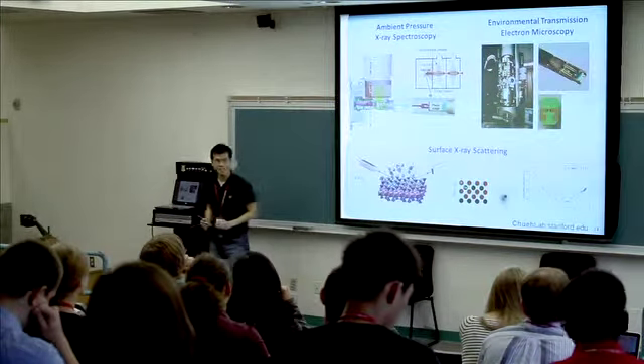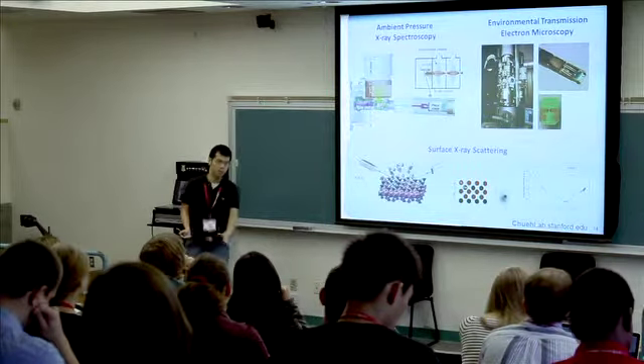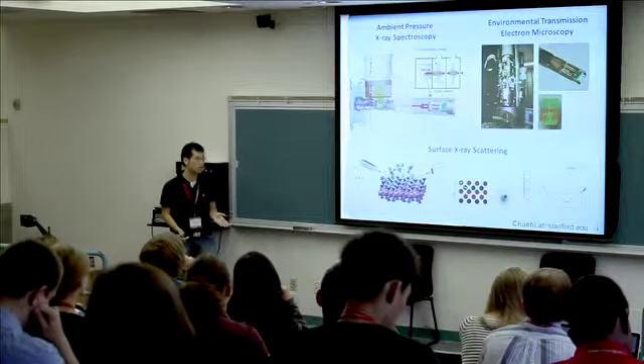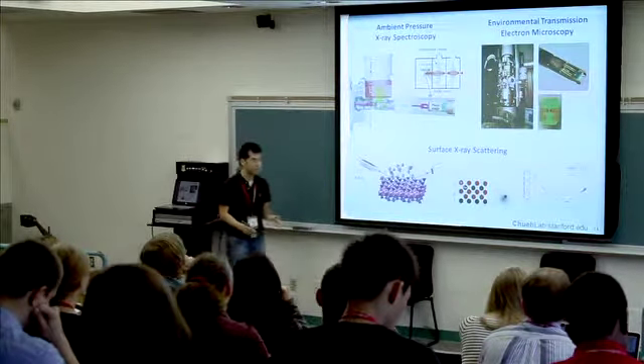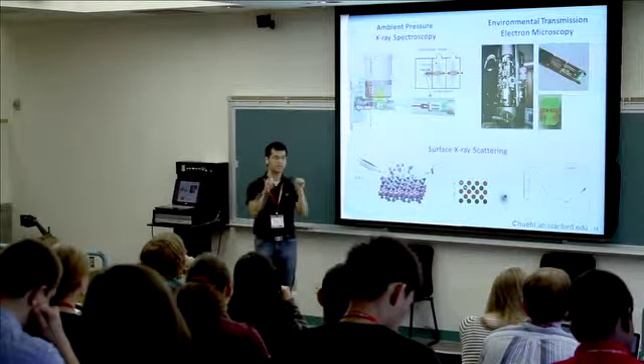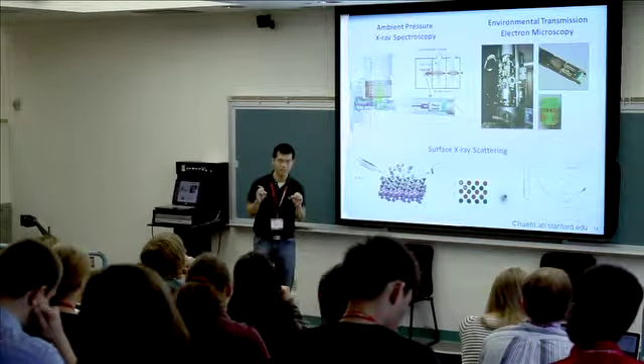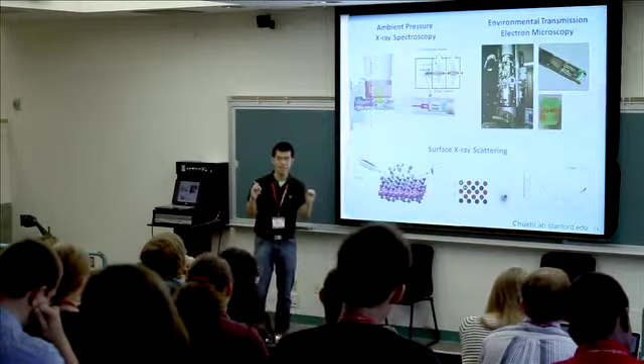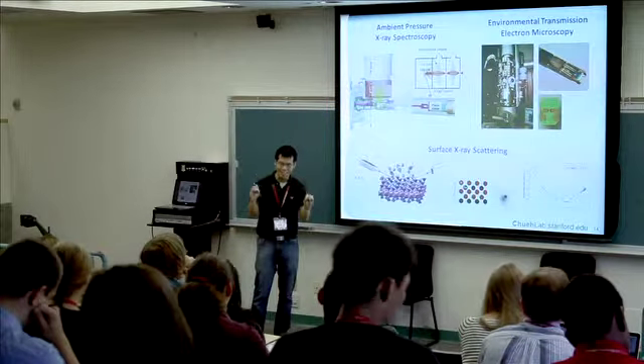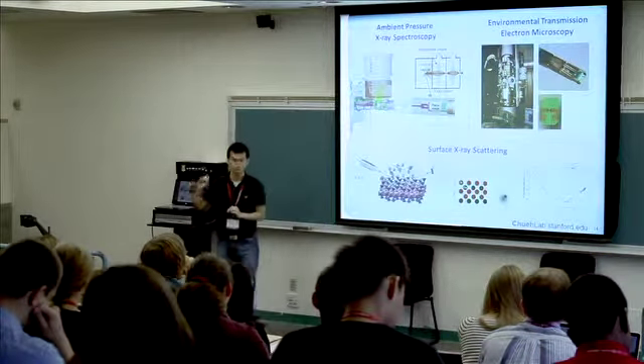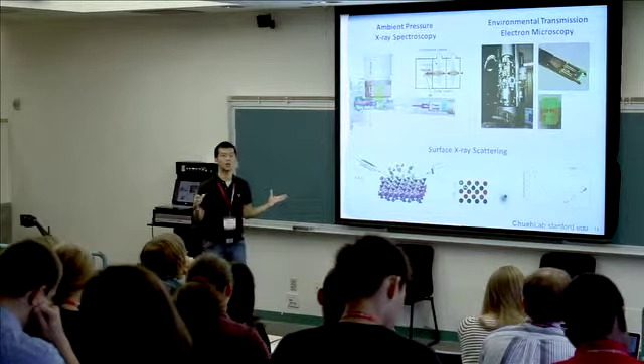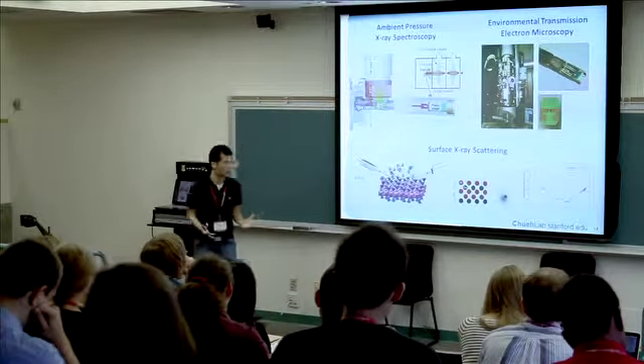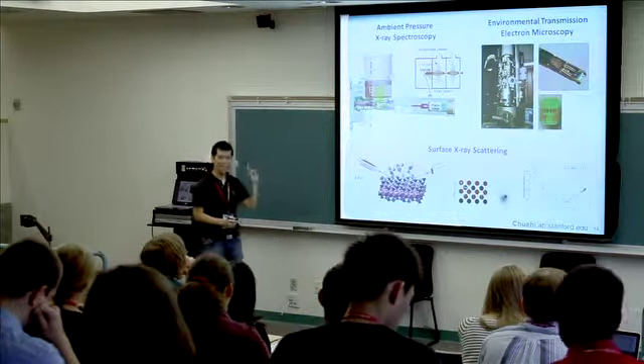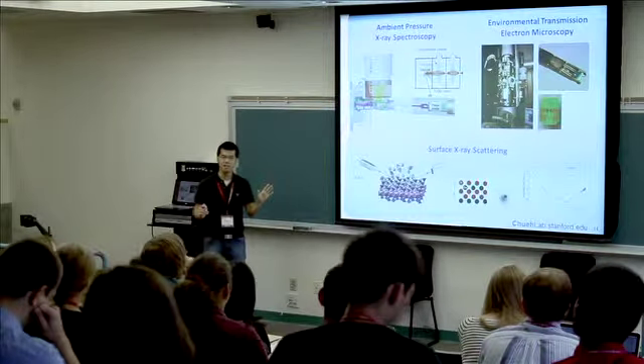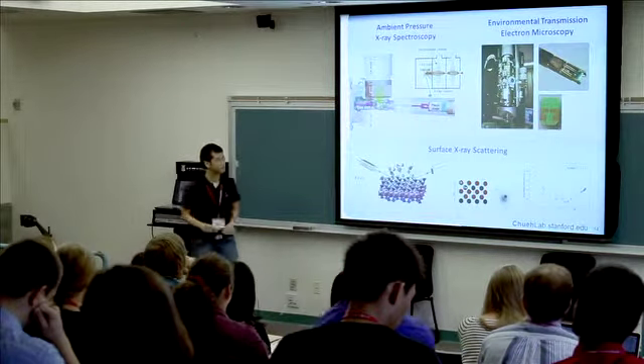This is mostly done at SLAC. We are shining X-ray light, and using a special technique called crystal truncation rod analysis, we can focus onto the top atomic layer of the catalyst. The very, very top, the atoms that intersect with the hydrogen, with the hydrocarbons. What does it look like? What is the structure of the material? And this is allowing us to look, again, not under static conditions, but under dynamic conditions.